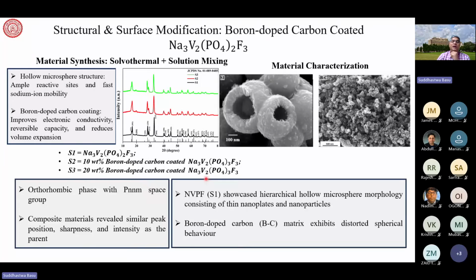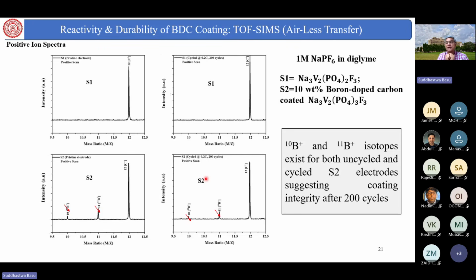So now, after studying the cell, we do a reactivity and durability study of the BDC coating with TOF-SIMS, time of flight secondary ion mass spectroscopy. We use airless transfer, with no contamination of air, with 1 molar NaPF6 in diglyme. We can see here the positive ion spectra. You can see for S1, where there is no BDC, at 0.2 C for 200 cycles, there is no peak.